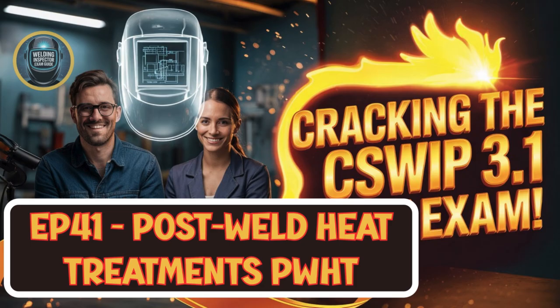A very common specification is 1 hour of soak time for every 25 millimeters. That's about 1 inch of material thickness, governed by the thickest part being treated. Okay, 1 hour per inch. And the last parameter, number 4. That's the maximum cooling rate.